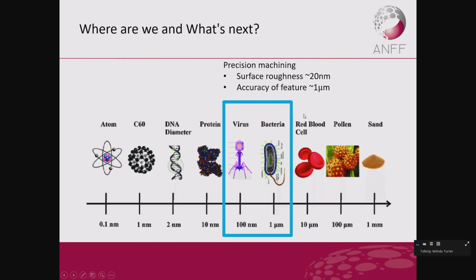So at the minute, we're down here with surface roughness around 20 nanometers. We've got less than that with the monocrystal diamond tools, accuracy of feature around 1 micron. So we recently moved to a new facility, and we built this home with all of those things in mind, like the temperature and the stability of the floor. So we built this home for the Kira, so we can optimize its efficiency, and we don't have to fight the room temperature and things like that. So it keeps the room within 0.2 of a degree during the day, and we're able to map that. We've got about 15 sensors in there now.